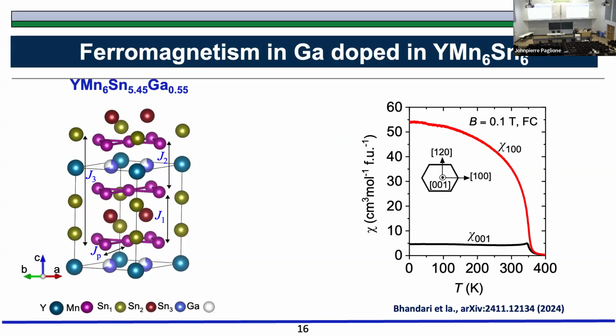The compound that we studied had this composition of gallium 0.55. It was replacing tin again on the same site, because calculations suggest that there is a huge preference for this replacement at the 2C site over any other site. And when we put in this gallium, you see the magnetism is completely changed now, right? It was antiferromagnet-like behavior or spiral states. Now, just by looking at this, you can say that, okay, this has become a ferromagnet with just a very small amount of gallium.